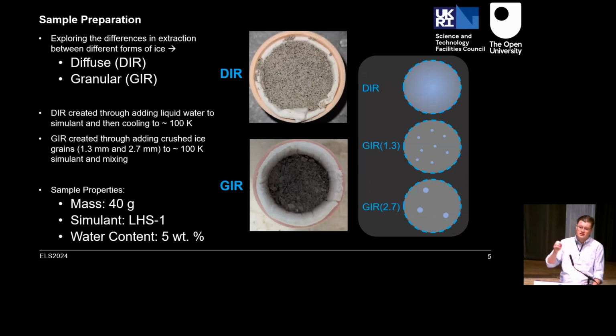Apart from that, as that was the only variable I wanted to look into, everything else was kept consistent. The mass of the sample was about 40 grams. The simulant was kept as LHS1, which is a Highland simulant, again most likely what the poles represent. And the water content was kept at 5 weight percent, targeting roughly the LCROSS results.